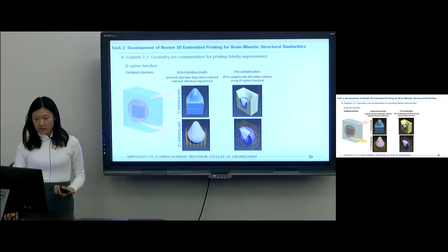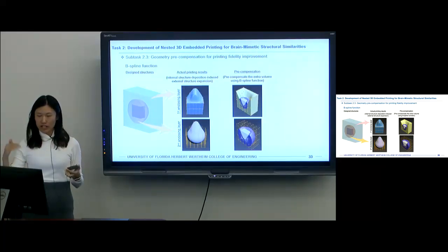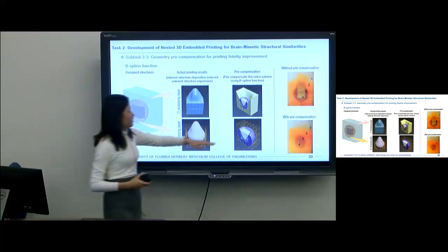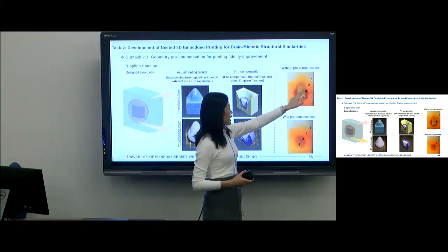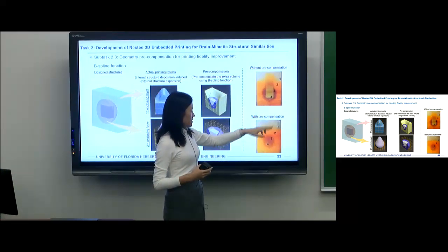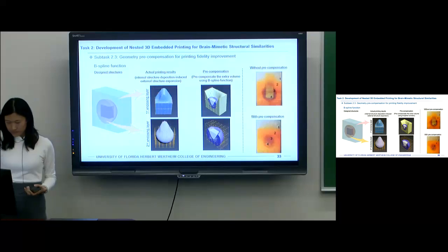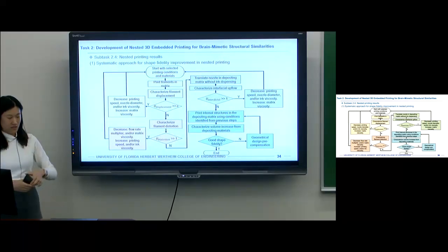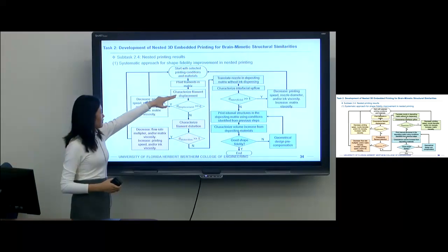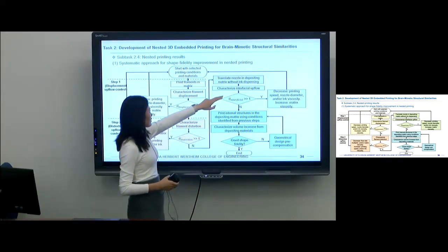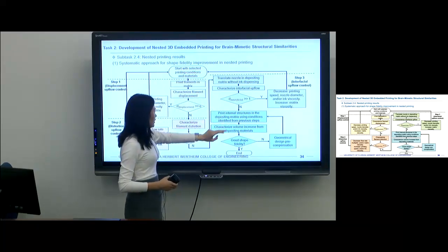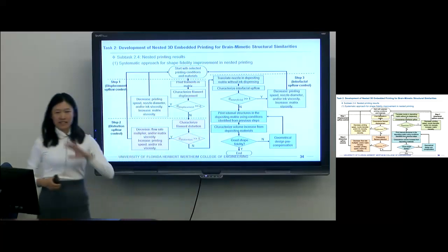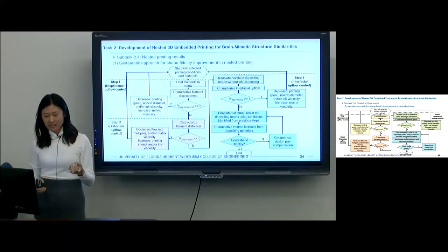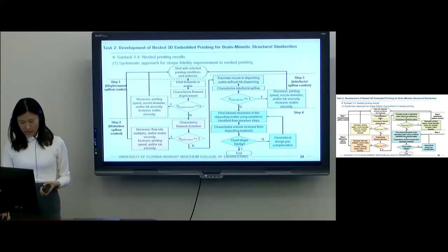To mitigate this kind of deformation, we used pre-compensation. Instead of depositing a perfect cube, we pre-compensate based on the volume that can extrude out. Without pre-compensation, we see the printed cube and the sphere are all deformed. With the pre-compensation, we can get decent enough structures. And that's the process. We try to mitigate the filament displacement, filament distortion, and use pre-compensation to mitigate both the printing upflow induced fidelity loss and the deposition volume induced fidelity loss.